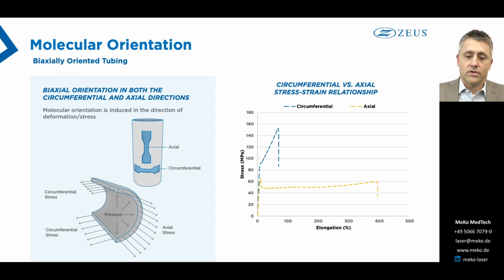So that blue curve is in the circumferential direction, which shows much higher orientation in that direction, much like the drawn fiber. And the yellow curve shows much lower orientation. And so in this particular case, the circumferential orientation really dominates. And that's by design for this particular tube for a certain scaffold. Not all scaffolds would benefit from this, but in this case, it does.